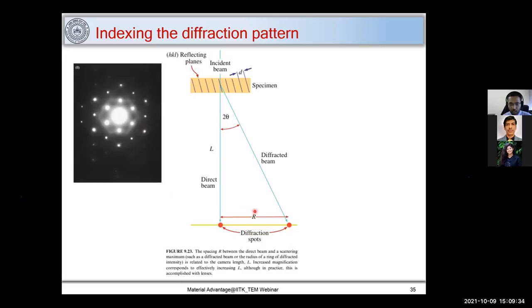Now, if I know this r, and if I use a standard specimen, let's say gold, I know the d, I know lambda, and I can find out this L. Now, when I configure my microscope using this relation, I can easily find out the d-spacings just based on measuring this r, which is the distance from a transmitted spot to a diffracted spot.